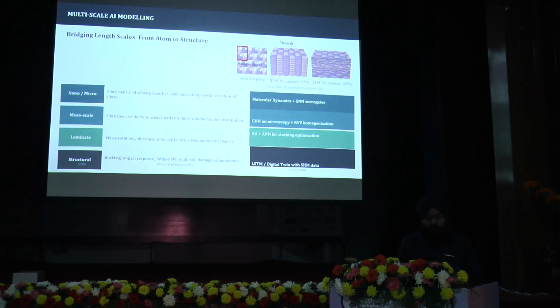Multi-scale artificial intelligence modeling covers nano or micro fiber-matrix interface properties, void nucleation, crystal structure of fibers, laminate ply orientation, thickness, interply failure mechanisms, and structural scales, where buckling, impact response, fatigue life and multi-scale damage accumulation matter.